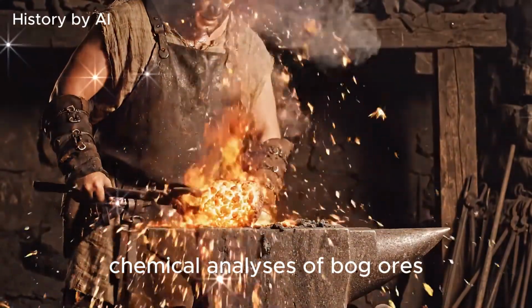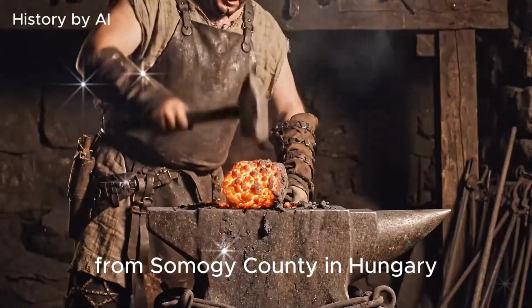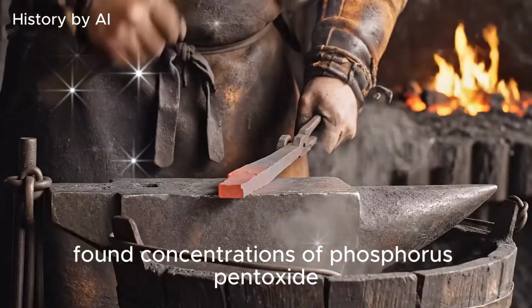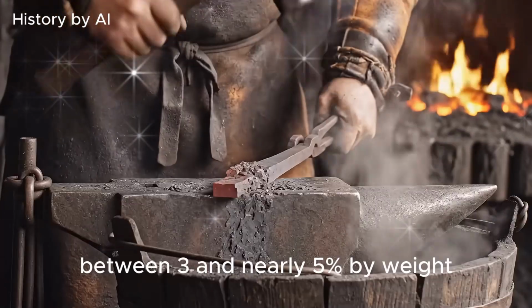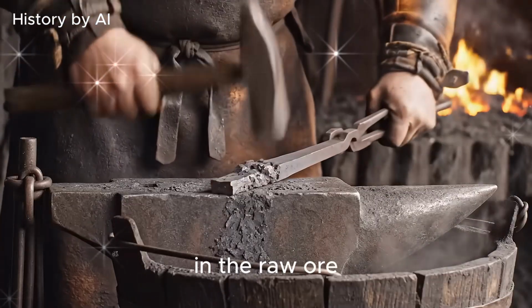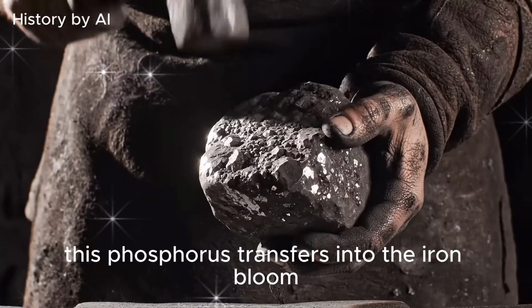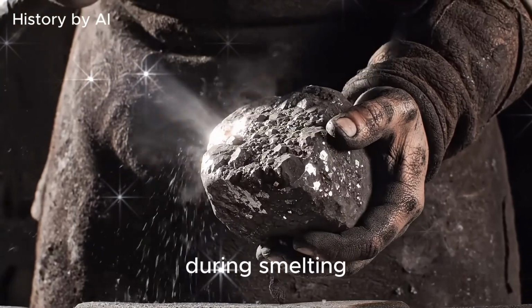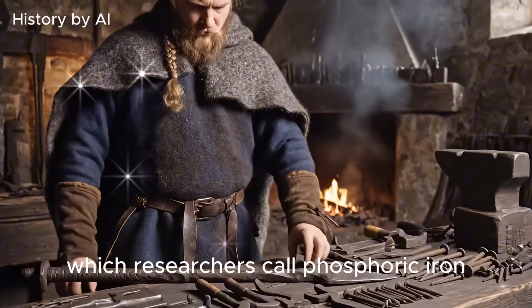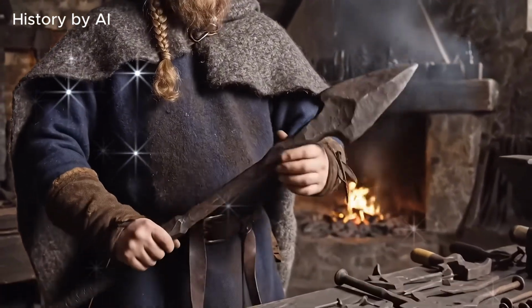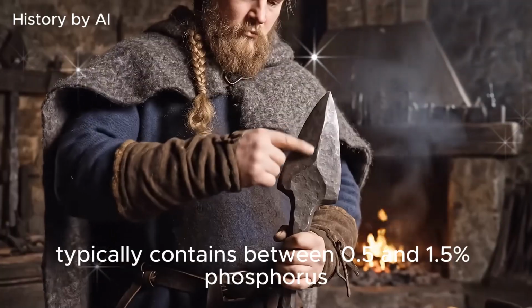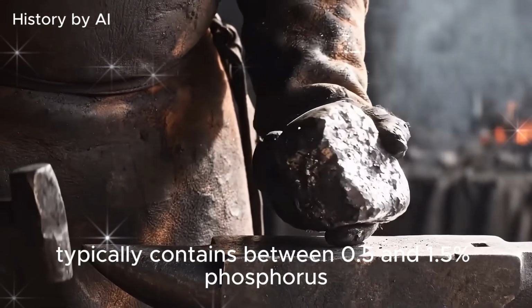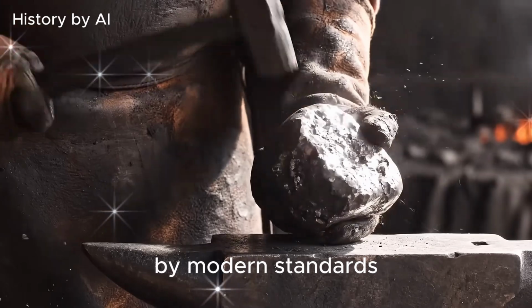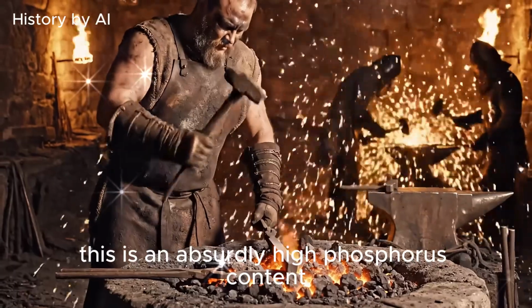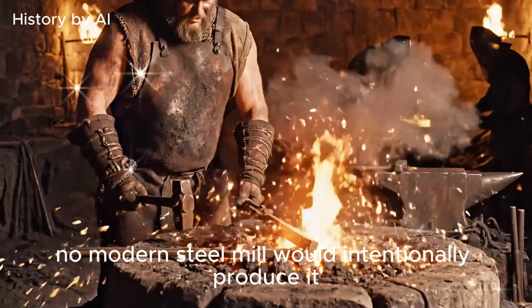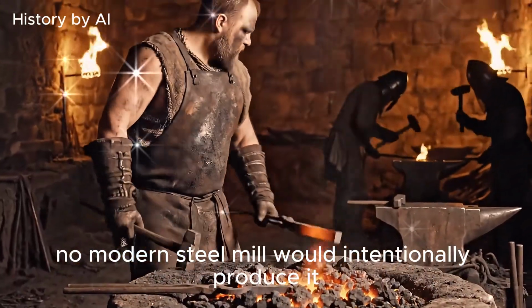Chemical analyses of bog ores from Somogy County in Hungary found concentrations of phosphorus pentoxide between 3 and nearly 5% by weight in the raw ore. This phosphorus transfers into the iron bloom during smelting. The resulting metal, which researchers call phosphoric iron, typically contains between 0.5 and 1.5% phosphorus by weight. By modern standards, this is an absurdly high phosphorus content. No modern steel mill would intentionally produce it.